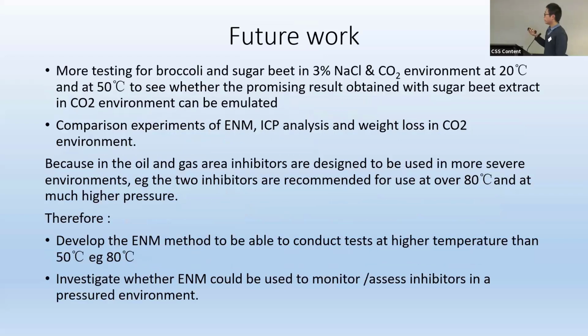So here's the further work. More testing for broccoli and sugar beet solution in 3% sodium chloride and saturated CO2 environment at room temperature and 50 to see whether we can repeat those promising results. And also probably do a comparison experiment for electrochemical noise Rn, ICP analysis and the traditional weight loss.